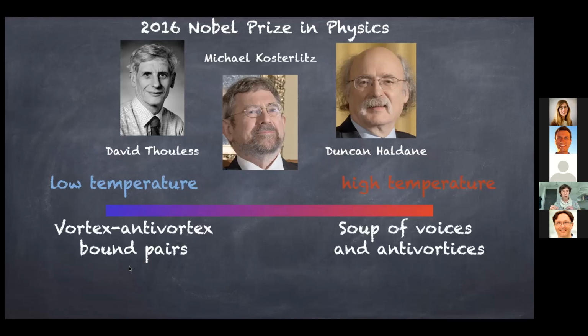But you can get these vortex-anti-vortex bound pairs as thermal fluctuations as the temperature starts to creep up from absolute 0. And at very high temperatures, you get such a high density of vortex-anti-vortex pairs that they basically lose track of who's partnered with who. And you get a soup of, sorry, that's vortices, not voices. It's autocorrect doing something there. You get a soup of vortices and anti-vortices dancing around.